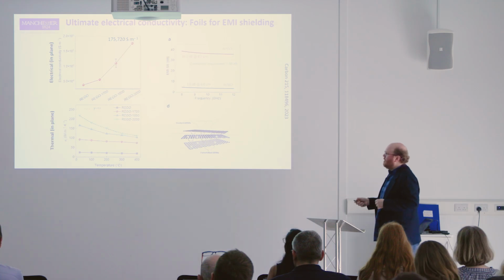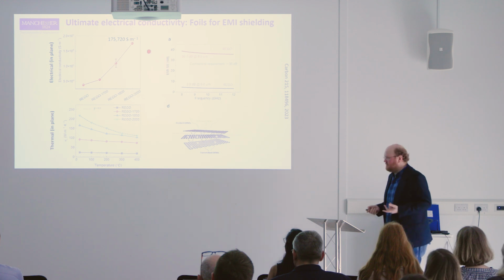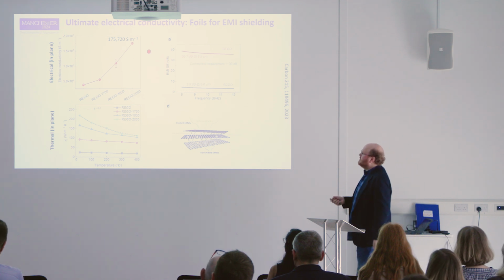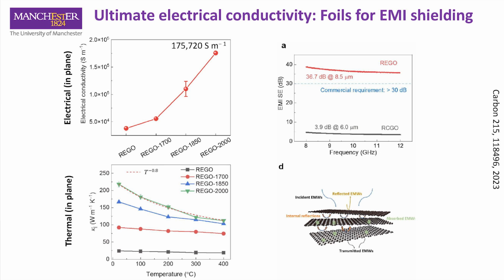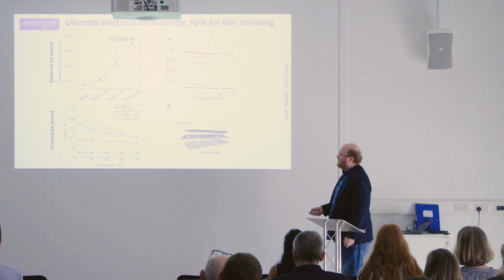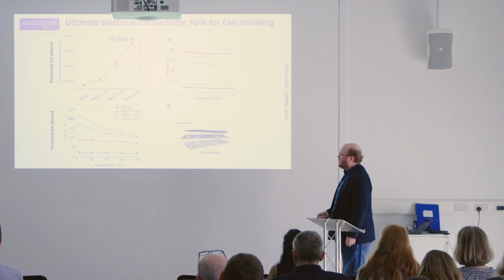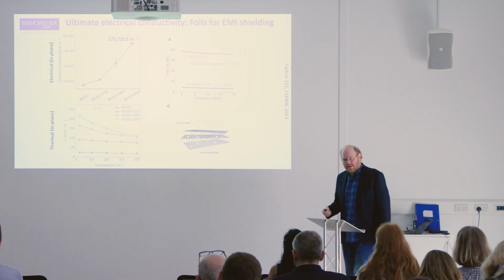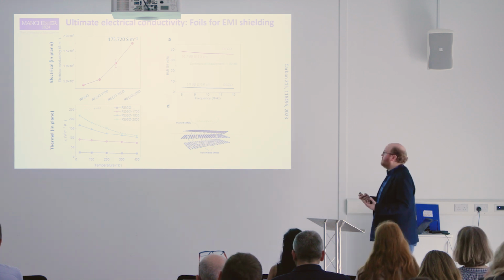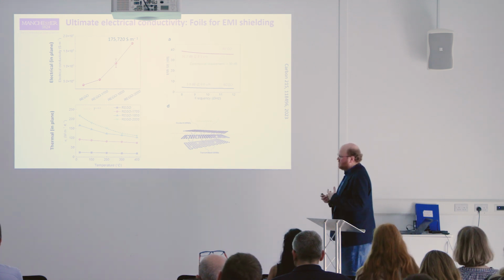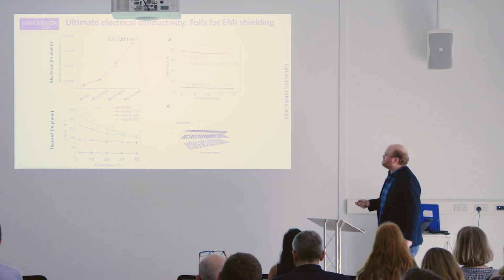And so that means that obviously we can get very high electrical conductivity of these foils. The electrochemically exfoliated graphene oxide starts off with a conductivity of about 10 to the 4. As we heat it up to 2,000 degrees and we repair all these defects, we can get conductivity of over 170,000, which is quite nice. In terms of thermal conductivity, we get over 200 watts per meter Kelvin, which is very, very high, much higher than we would get for, say, even graphite. So it makes it quite attractive for use in heat spreaders.